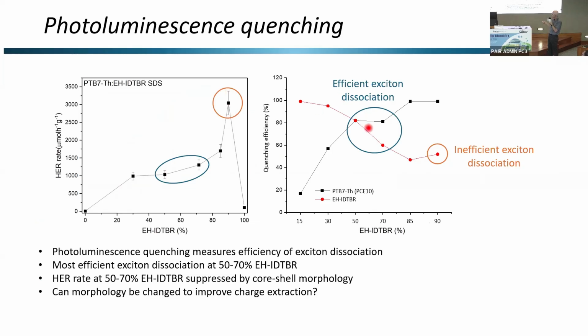this maximum at 90% doesn't really match efficient exciton dissociation. So if you look at the exciton quenching efficiency of the donor and the acceptor, you'll see that ideally for a solar cell combination, you want to be around 50%. That's 50, 60% is ideal for a solar cell. In our case, the maximum HER rate is at 90%. So that's really inefficient here for our exciton dissociation of our acceptor. So this setup is not really delivering the charges that we'd like to see.